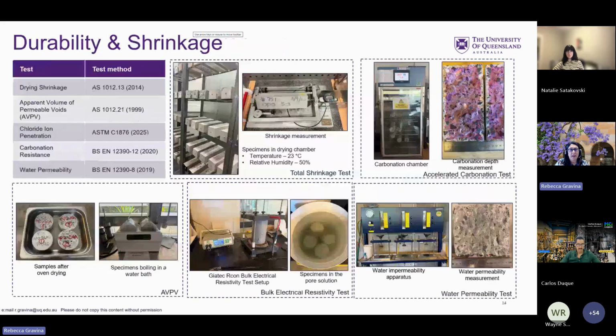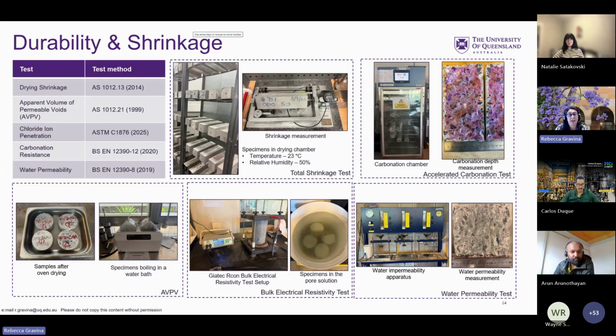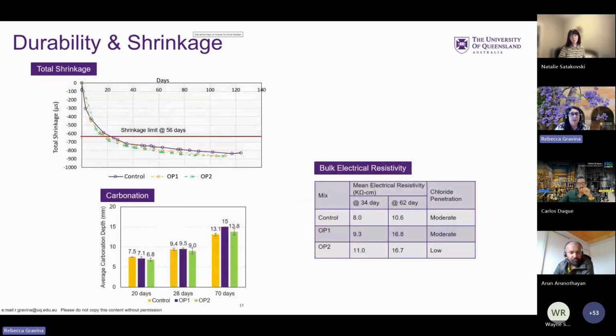In terms of the durability properties, we've carried out tests on drying shrinkage, the apparent volume of permeable voids, chloride ion penetration, carbonation resistance, and water permeability. And you can see the test methods that we have worked towards, and the equipment that was used in the labs at UQ here in St Lucia. And just to show some of the results, and not all of the results,